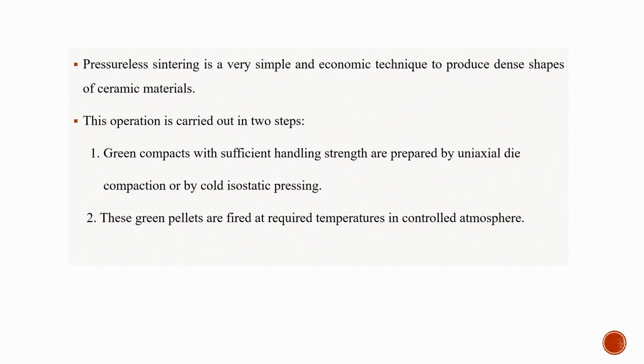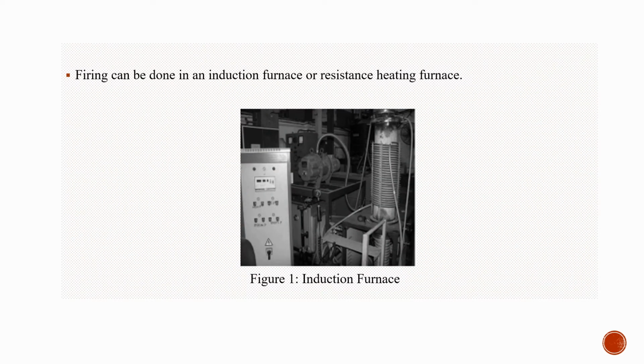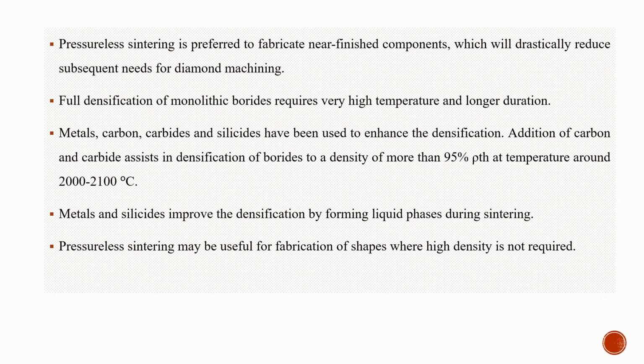Pressureless sintering is a very simple and economic technique to produce dense shapes of ceramic materials. This operation is carried out in 2 steps. 1. Green compacts with sufficient handling strength are prepared by uniaxial die compaction or by cold isostatic pressing. 2. These green pellets are fired at required temperatures in controlled atmosphere. Firing can be done in an induction furnace or resistance heating furnace. Figure 1 shows the induction furnace. Pressureless sintering is preferred to fabricate near-finished components, which will drastically reduce subsequent needs for diamond machining.